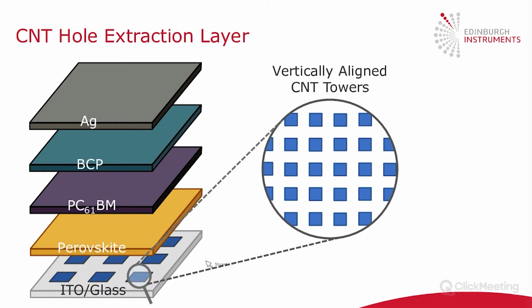So we start with an ITO glass, and then deposited on the ITO glass are carbon nanotube towers. And the idea of these is to act as a hole extraction layer. So you generate charge carriers in your perovskite, so electrons and holes. And to get a good solar cell, you need to get the electrons to go to one of your electrodes and the holes to go to the other.